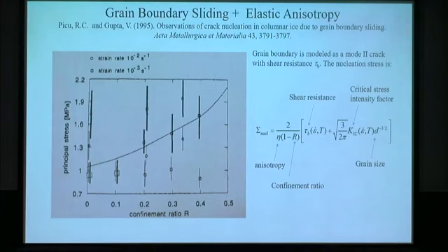We can conclude that whenever we try to predict crack nucleation, if no cracks existed before, we need to have some sufficiently strong singularity. Elastic anisotropy, according to some analysis, is not strong enough. But according to my analysis, it could be sufficiently strong, because of the variability: the crystal is not a regular hexagon. You could have two triple points which are close to each other.